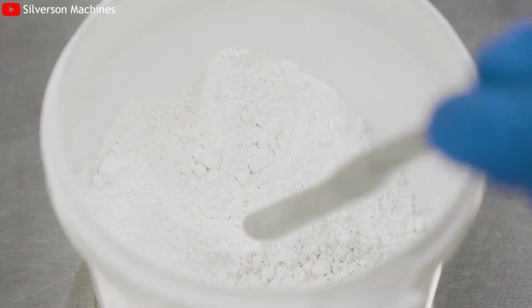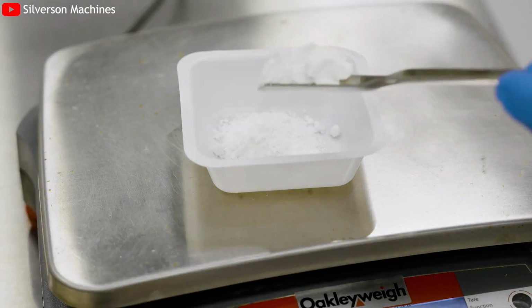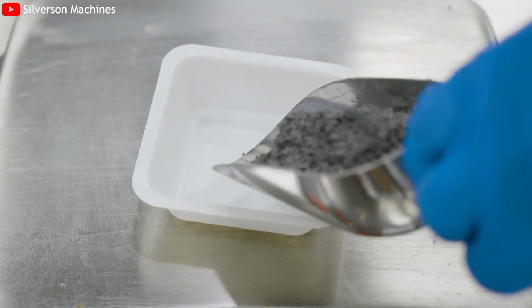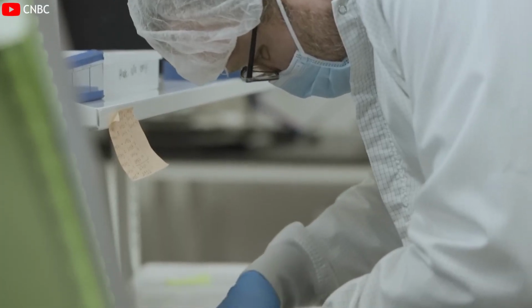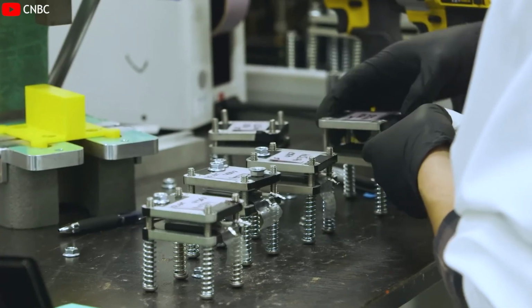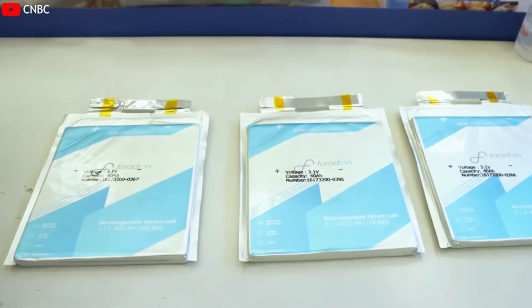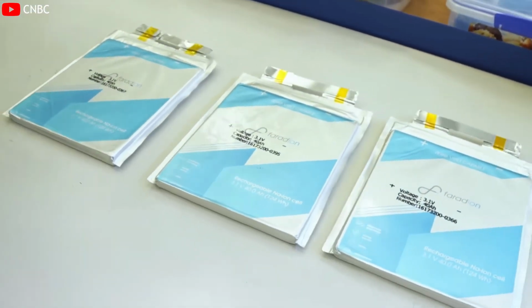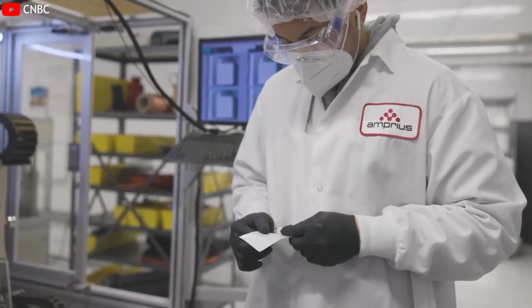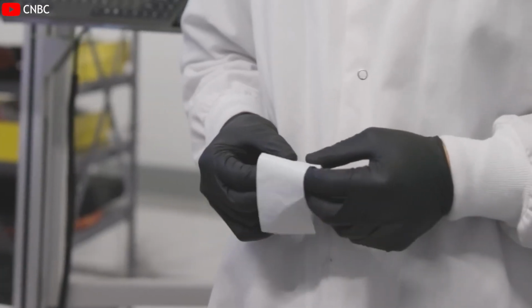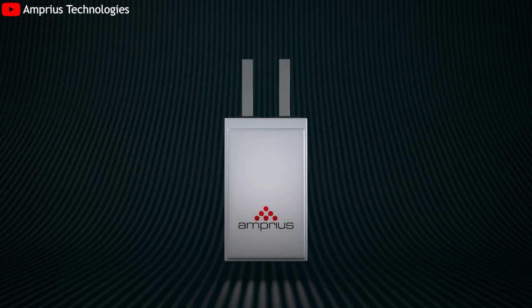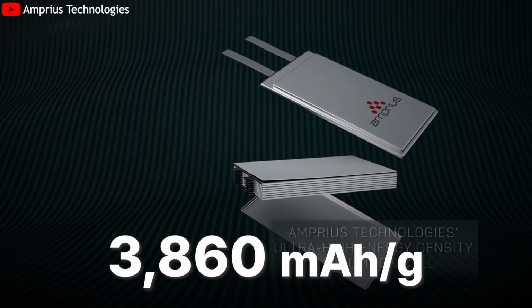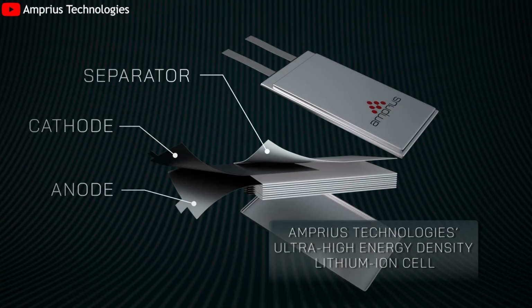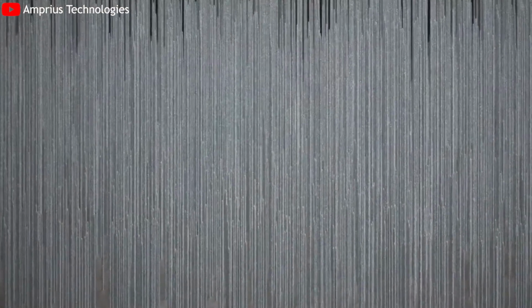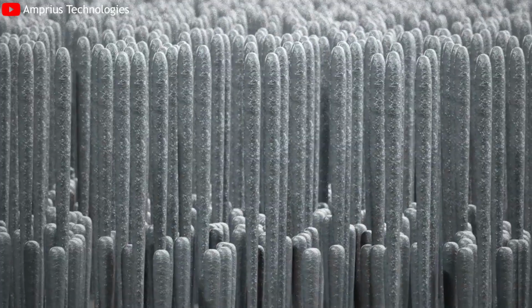Startups fail because they are trying to integrate a laboratory experiment that requires industrial clamping force into a vehicle that demands lightweight and flexibility. We were promised a ceramic shield that would prevent explosions. Instead, we were given a ceramic sieve. Why do these unbreakable batteries still short-circuit? The core value proposition of solid-state batteries lies in the ability to use a lithium metal anode. This offers a theoretical capacity of 3,860 mAh per gram, 10 times higher than graphite. The theory is simple. A hard ceramic electrolyte should physically block lithium dendrites from penetrating and causing short circuits. That theory is fundamentally wrong.